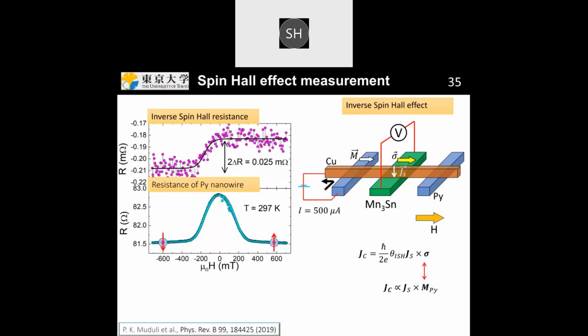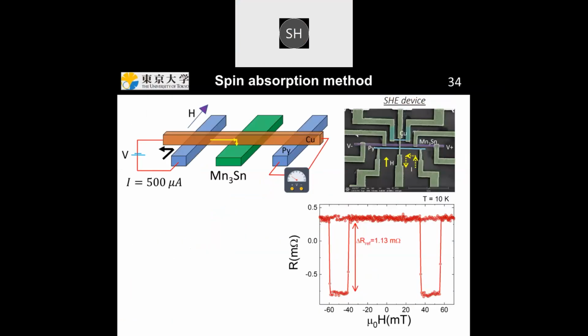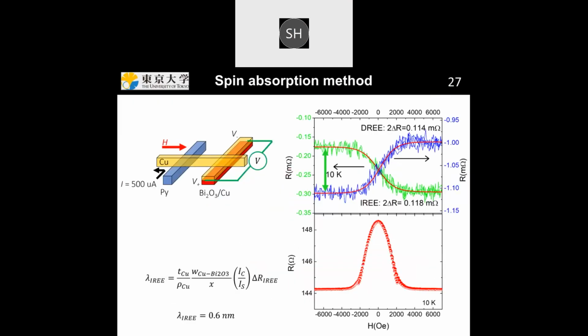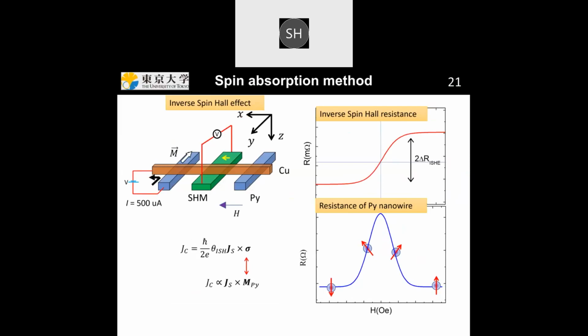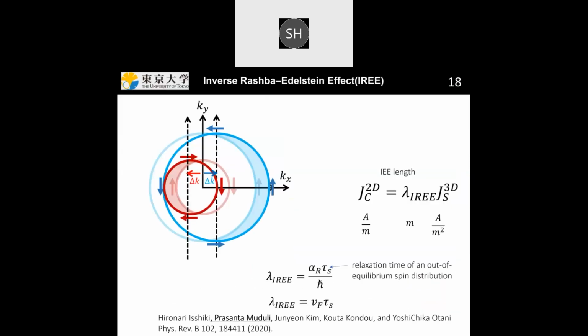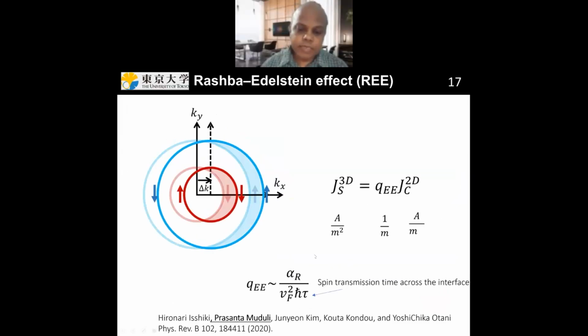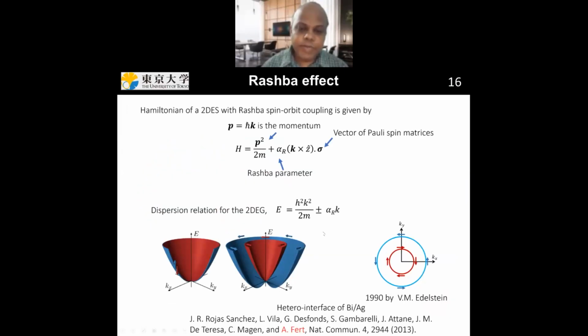Yeah, I have one very basic question. In case of spin Hall effect based materials like platinum or tungsten, the spin Hall angle depends on the SOC strength, spin orbit coupling strength. So for your Rashba-Edelstein interface, what parameter or property of the material is crucial? The crucial parameter is the Rashba parameter, this alpha, which quantifies the splitting. This alpha is the most critical parameter for spin charge conversion. It's not a material property, this is an interface property. So depending on different material, different interface, you will have different alpha.